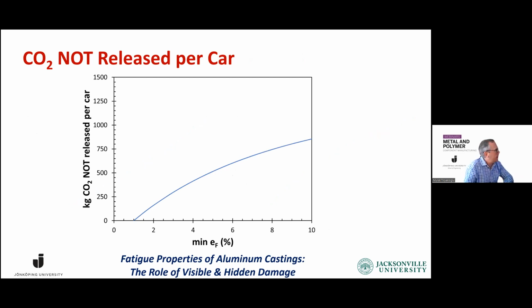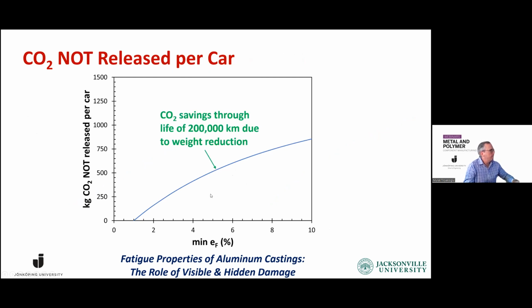Then, carbon dioxide not released per car. This is after 200,000 kilometers. Because the car is now lighter, it's no longer 2 tons, maybe it's 1,900 kilograms. It produces less carbon dioxide with everything else the same. So I plotted that. You can see that we can go up to about, I would say, 800 kilograms of carbon dioxide not released just by increasing our expectation from castings.